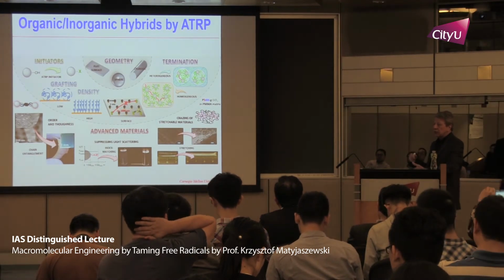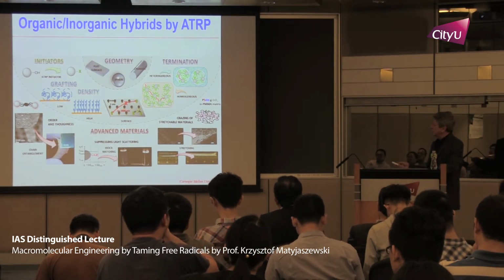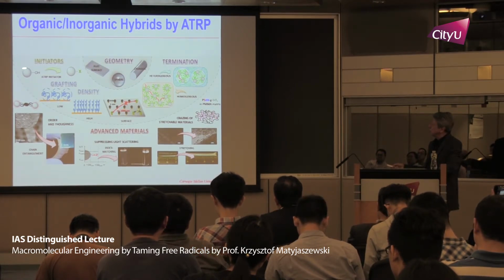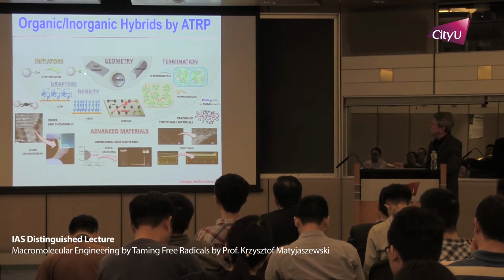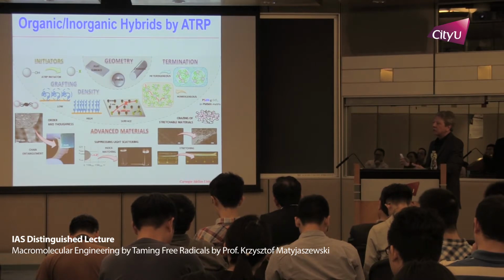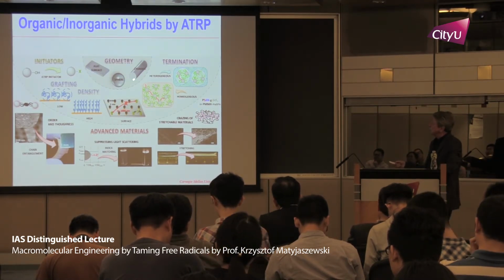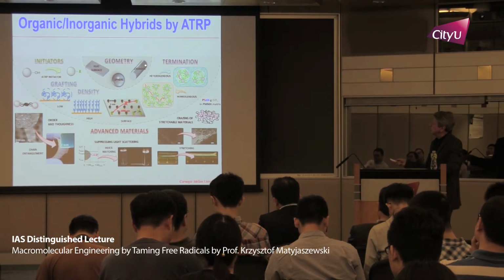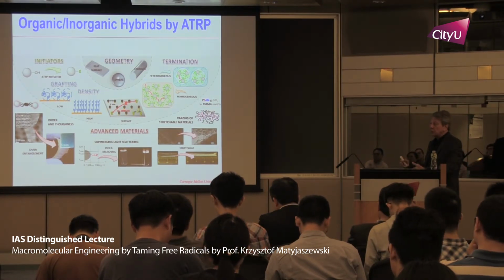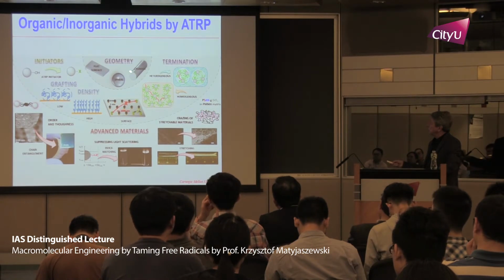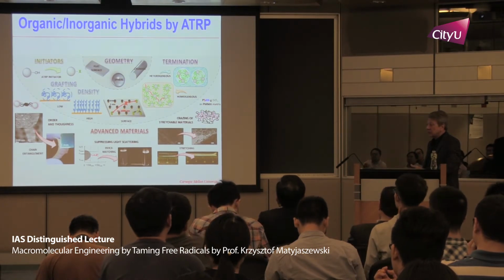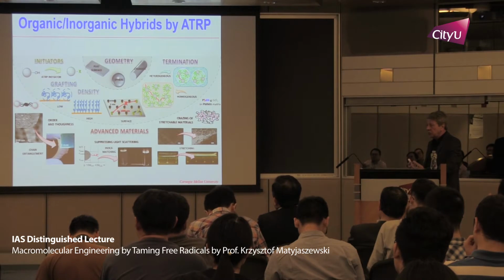An analogous approach is really when we use organic-inorganic hybrids. Instead of the natural products, we use inorganics. And this starts with putting functionality, for example, on a silica. So instead of silanol groups, we now have bromoesters. And then we grow polymer chains with a certain accuracy. We can do it from flat surfaces, from nanoparticles. We can start from cylindrical, for example, mesoporous silica. It can be from outside, can be inside as well. And you can form very uniform structures.